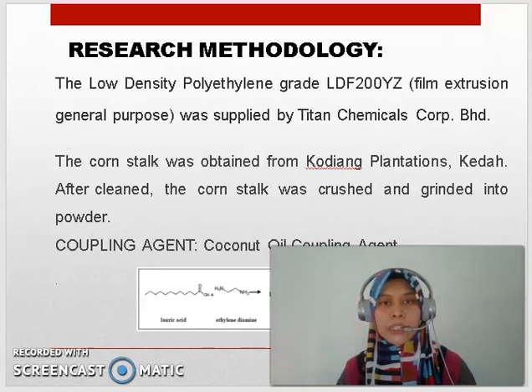Our research methodology. The low-density polyethylene grade LDF200YZ film extrusion general purpose was supplied by Titan Chemicals Corp. Berhad. The cornstalk was obtained from Kodiang Plantations, Kedah. After being cleaned, the cornstalk was crushed and ground into powder. Our coupling agent used is coconut oil coupling agent.